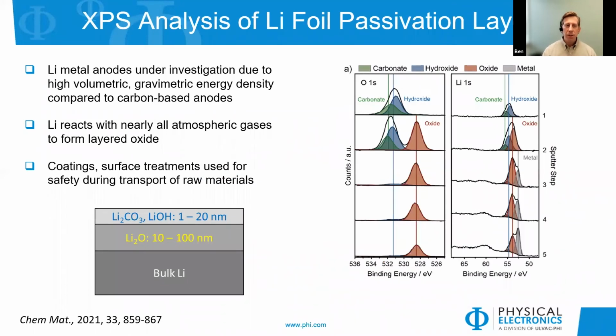So getting into our first example, we want to look at how we can use XPS analysis to understand the passivation layer on, say, a lithium anode foil. Lithium foils are under investigation as replacements for carbon-based anodes, just because they have high volumetric and gravimetric energy density compared to carbon-based anodes. But there are some problems, especially with this very high reactivity and being able to control that as you then combine this with other electrolyte materials and so on.